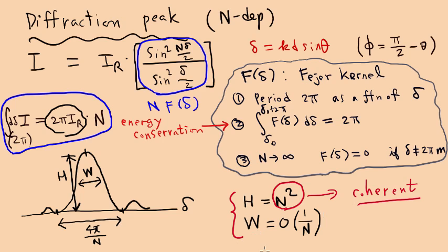That's one possibility. You can also do X-ray diffraction, and the width of this peak will tell you the width of your crystallites. So the fact that the width is 4 pi over n can be used to measure the n value of your crystalline sample.